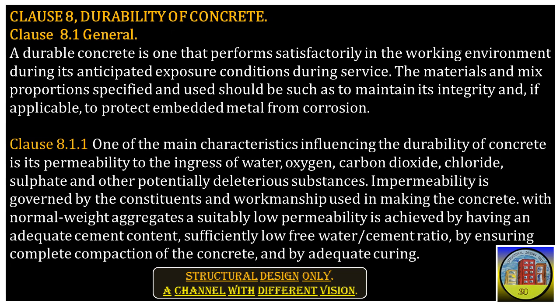Clause 8.1.1: One of the main characteristics influencing the durability of concrete is its permeability to the ingress of water, oxygen, carbon dioxide, chloride, sulfate and other potentially deleterious substances. Impermeability is governed by the constituents and workmanship used in making the concrete. With normal weight aggregates, a suitably low permeability is achieved by having an adequate cement content, sufficiently low free water/cement ratio, by ensuring complete compaction of the concrete, and by adequate curing.